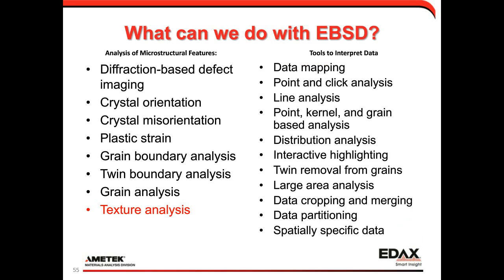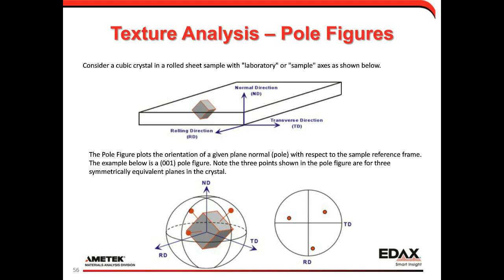So one of the things we can talk about is texture analysis or preferred orientation analysis. Just as a quick review, I'm going to show what we call a pole figure. A pole figure shows the distribution of a given crystallographic plane relative to a physical sample surface. In this case, we often talk about the normal direction of a sample, and that's just the direction coming out of the sample surface. But we can also have in our measurement frame an RD, a reference or rolling direction, or a transverse direction which is orthogonal to that. If you imagine your right-hand rule, your normal is often your thumb, your RD is often your index finger pointing down the direction of tilt, and your transverse direction is 90 degrees to both of those.